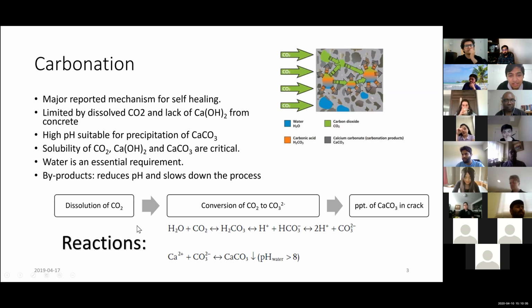As you can see, while carbon dioxide from the atmosphere is dissolved, two hydrogen ions are released, and this leads to a lowering of the pH. So the pH lowers and it slows down this process in itself. Also, with a lowering of the pH, we can get an early initiation of corrosion in concrete. That's why, as you may all know, carbonation is not favored in concrete for durability.